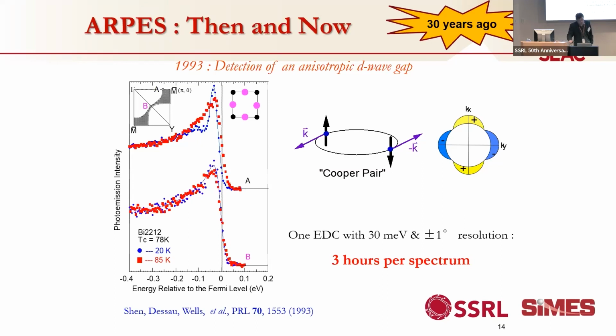So if you look at the spectra taken at point B, you can see that the red and the blue data are more or less the same. There's no difference above and below the transition temperature. But when you look at point A, you can see a clear difference between blue and red data. That was the first indication that we may have an asymmetric pairing because it's an angular dependence. And the way the asymmetry works turned out to be very consistent with d-wave pairing.